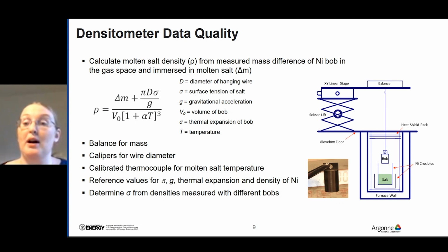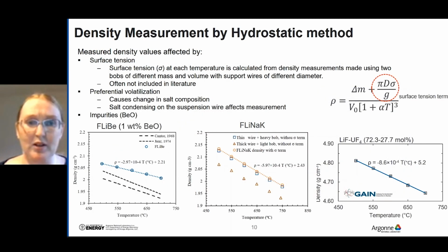And so in order to apply quality assurance to this, you have to do it to each of the parameters in the equation. So for example, for the mass, we know the uncertainty of the balance. We can calibrate and check it. For the wire diameter, we use calibrated calipers. We can verify the temperature with a calibrated thermocouple. We can use established reference values for all of the constants. And then, of course, this equation also contains a surface tension term, and we directly measure that using this technique with two different bobs. I'll talk about that here on this slide.